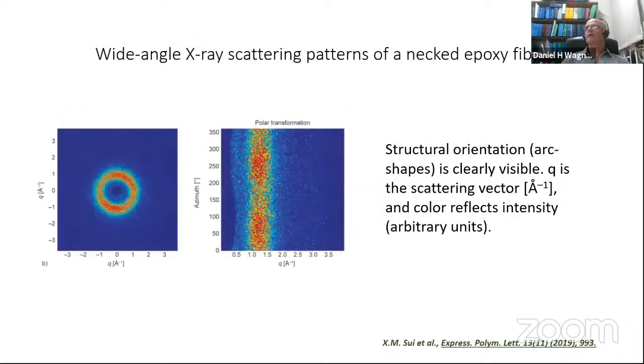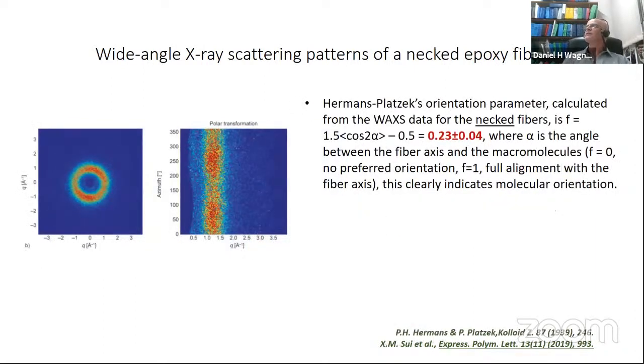But there is some molecular reorientation. This is the evidence that we found. You see, when you have an arc shape like you have on the left picture, it means that you have an oriented fiber, actually. And we did some calculations using the orientation parameter, the Hermans-Platzek orientation parameter, which you can calculate from the WAXS data for the necked fiber, and it's 0.23, which demonstrates that it's not a very high reorientation, but it's not